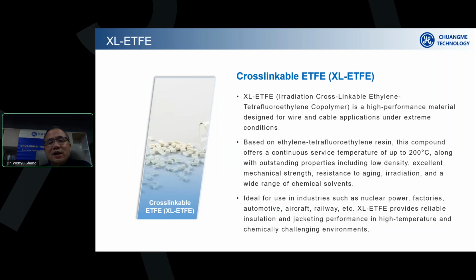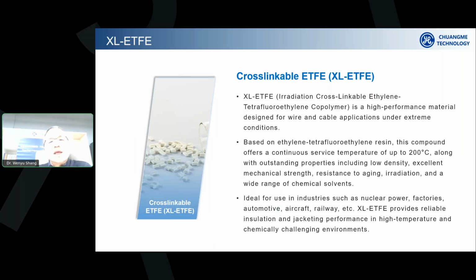As you can see, cross-linkable ETFE, XL-ETFE, and the working mechanism of this material is we take a specialized ETFE and compound it into a specialty formulation, which contains ETFE as the base resin, plus the radiation cross-linking agent and other supporting agents, and make the whole material radiation cross-linkable. Now, when the customer takes the material and co-extrudes it onto the wire core, the copper wire core, they then put the cable in an E-beam, electron beam radiation machine, to cross-link the insulation layer and make the whole cable finalized as a cross-linked ETFE communication cable.